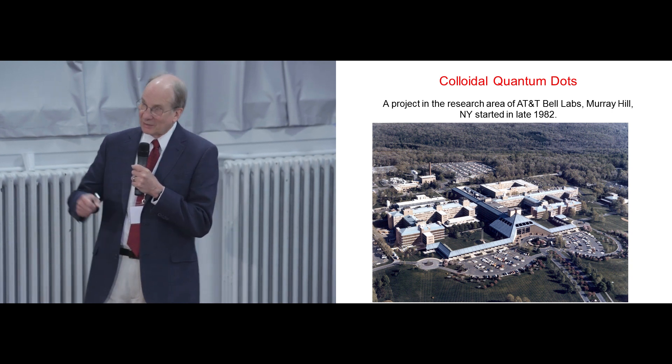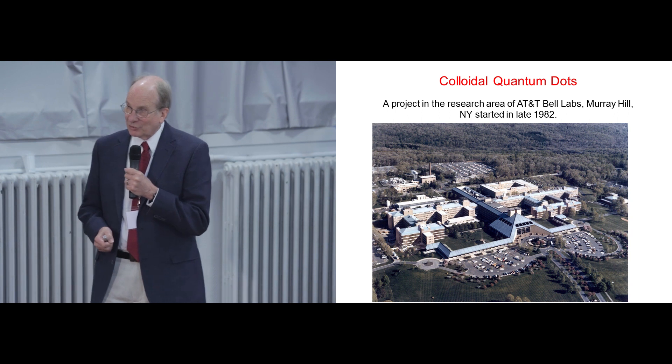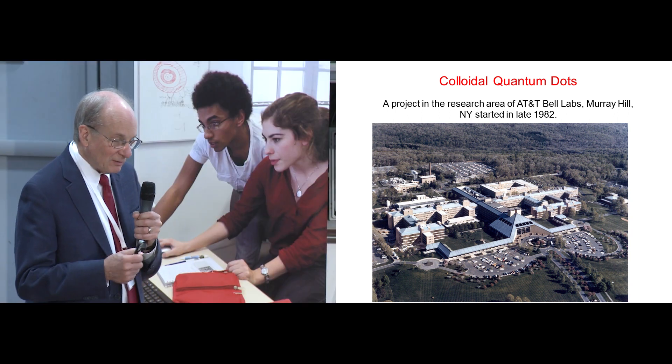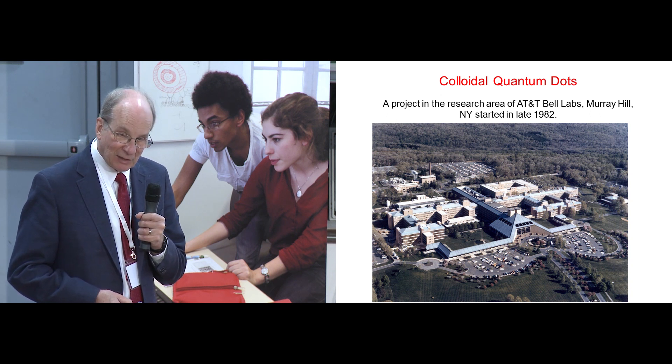And it was a size effect. The first day, the particles were smaller. The second day, they were getting to be larger. And so that really got my attention, as you might imagine.